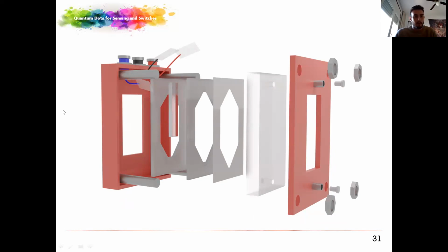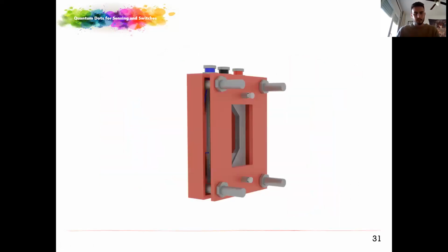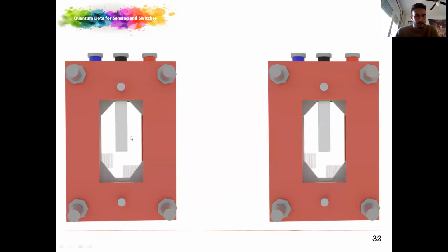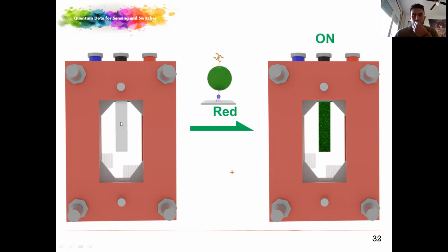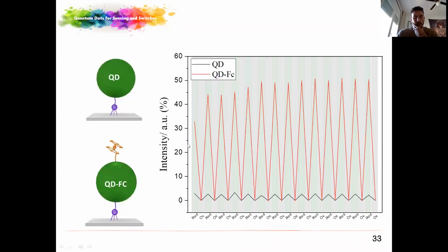For that, we fabricated a device, which probably many of you know, this infrared setup for liquid samples. We modified this setup in order to use a surface with electrochemistry inside for optical measurements. It's a front view of this device, and this is the conductive surface containing the quantum dots and the sample. After the reduction, we observe an on-off situation. With a reduction we have an on situation, and with oxidation, off. And this is the switch we found.